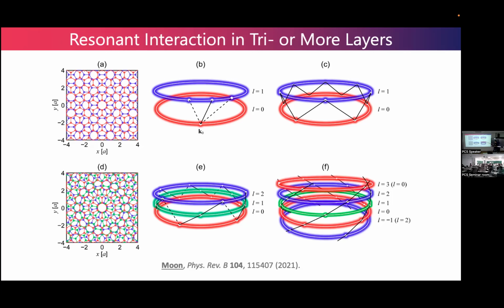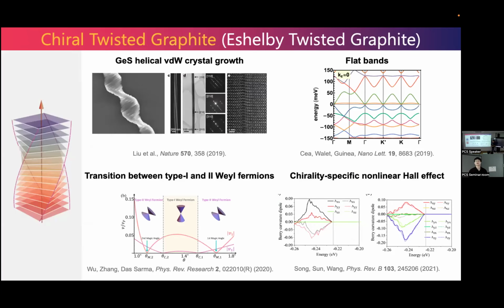However, if we stack another layer, the red layer on top of the blue layer, then it satisfies the momentum conservation, and also the interaction strength becomes equivalent, identical. If you do this, continue to the infinite z direction, then we can make the resonant state with spiral symmetry. Just for fun. Such a chiral structure is not very common, but there are several examples, and it is expected that many interesting features arise in such structures.